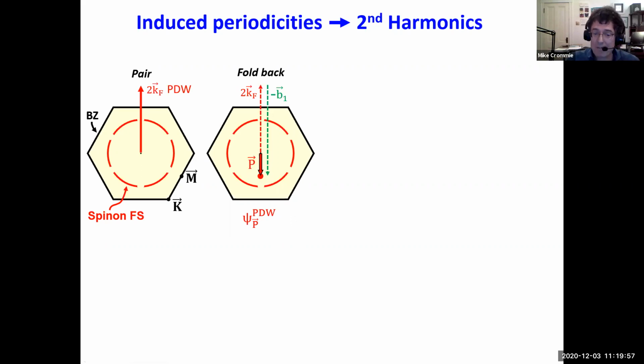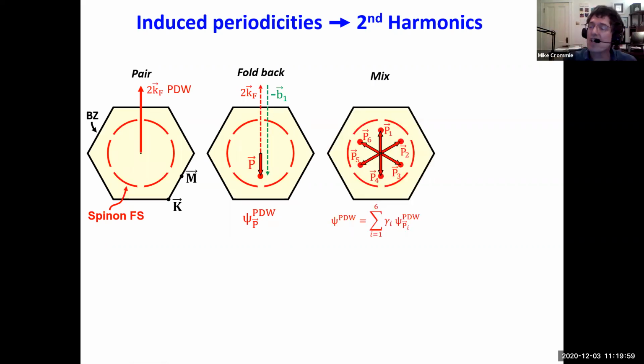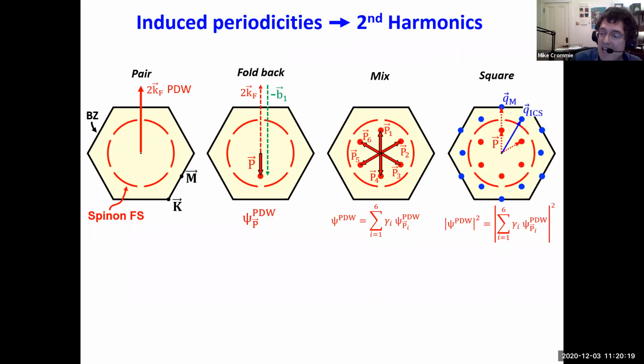But this happens simultaneously for all 6 directions. And so we expect that the pair density wave should have components from all 6 of these directions due to coupling via scattering from defects and also scattering from spinons. This is what we expect the wave function of the pair density wave to look like. We can then ask, what do we expect the state density of the pair density wave to look like? We just square that. And if we square it, we get these second harmonics, these blue dots.